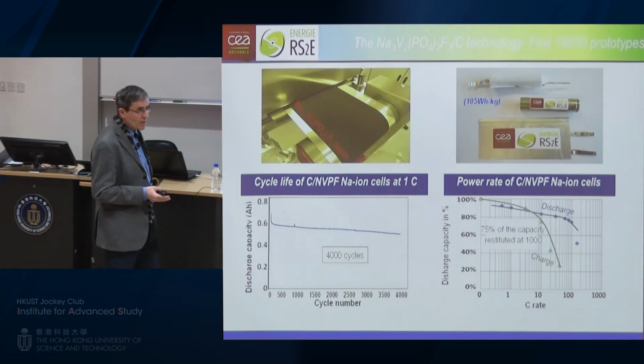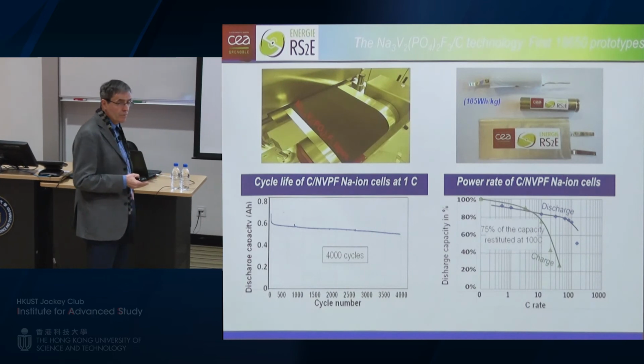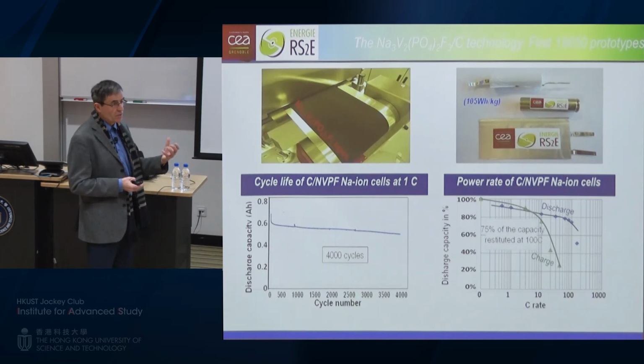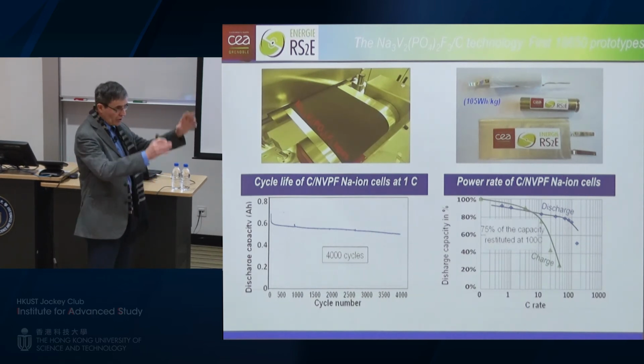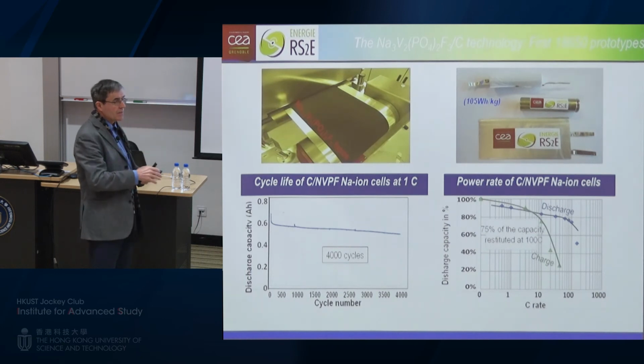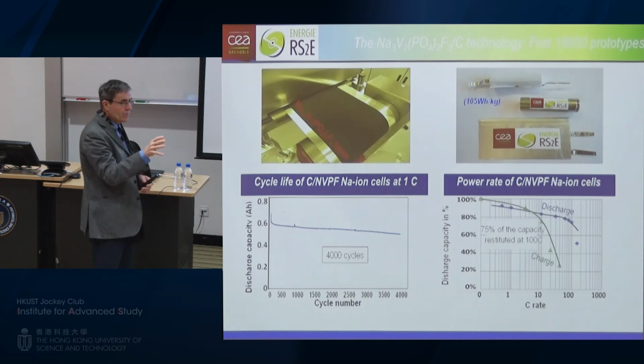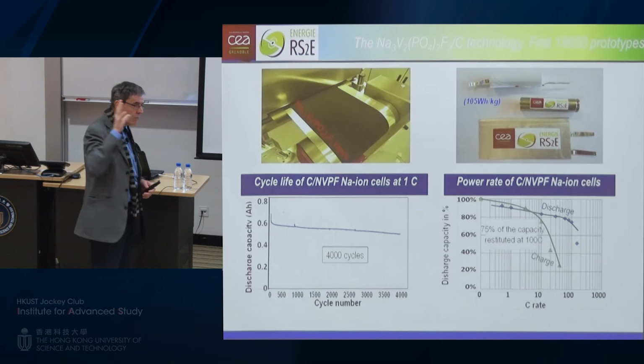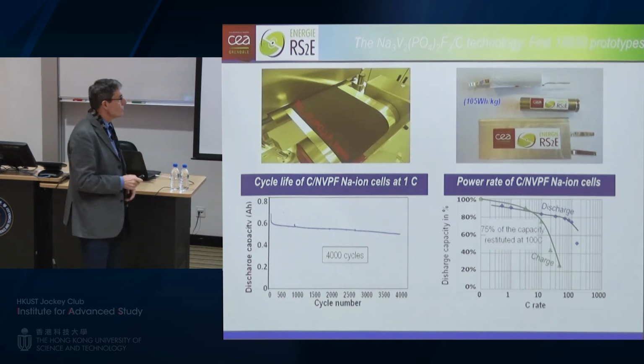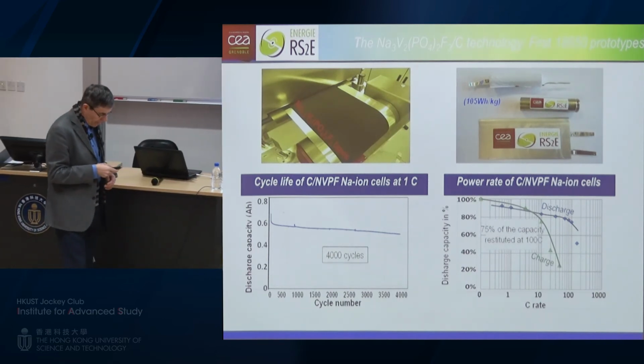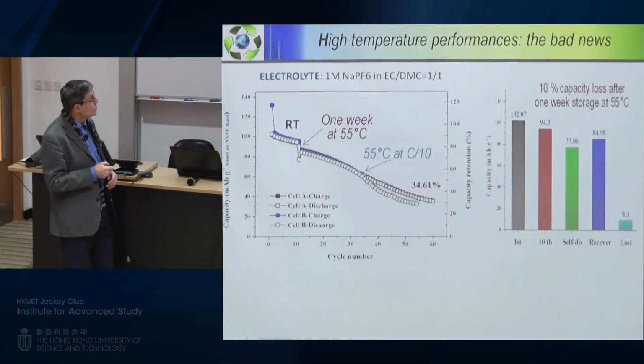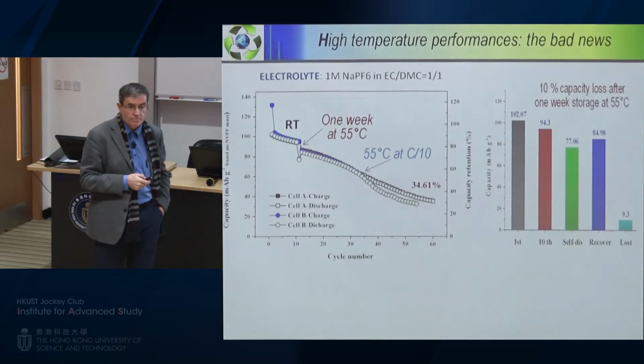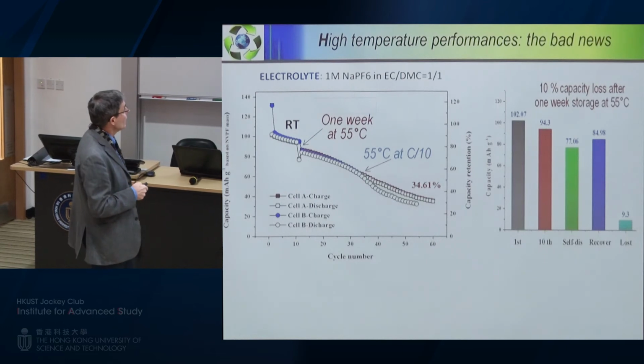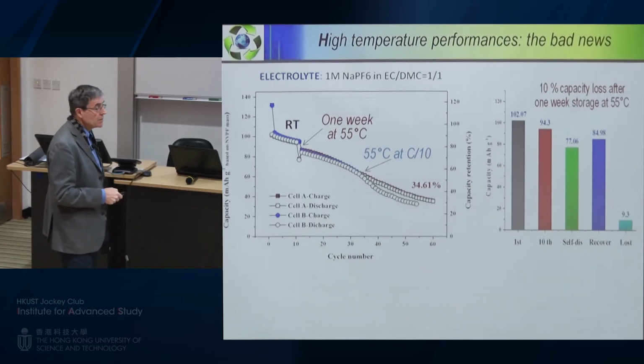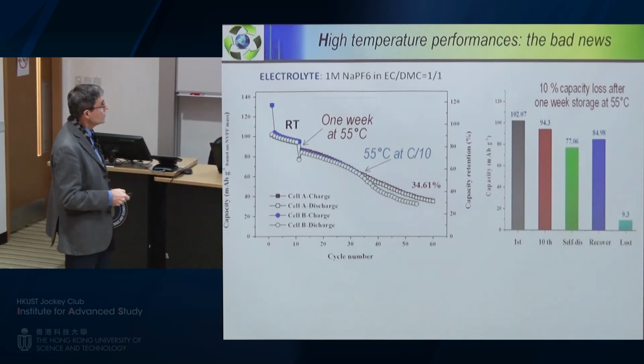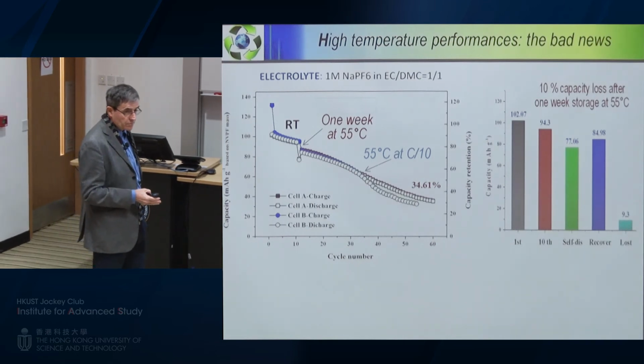And this may sound counterintuitive, since sodium is bigger than lithium, but you need to realize that you have channels, you have oxygen around it. Since the charge is delocalized on sodium, the sodium will move faster than lithium. So everything was good, except that we then tried to go to high temperature. And we went to high temperature. You can see here some cycling, some cell discharge, and so on. It was a total disaster.